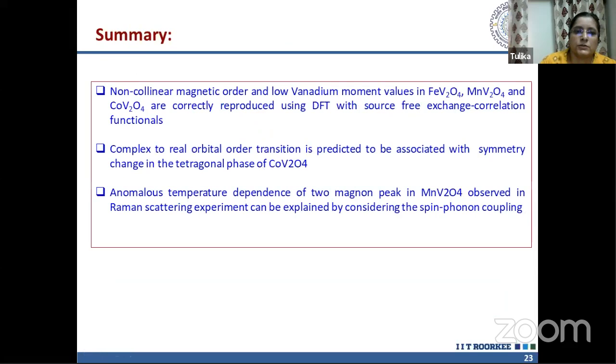Okay, so this is the summary. Non-collinear magnetic order and low vanadium moment values are correctly reproduced using DFT with source-free exchange correlation functional, and the anomalous temperature dependence of two magnon peak in MnV2O4 was possible to explain by considering this spin phonon coupling.